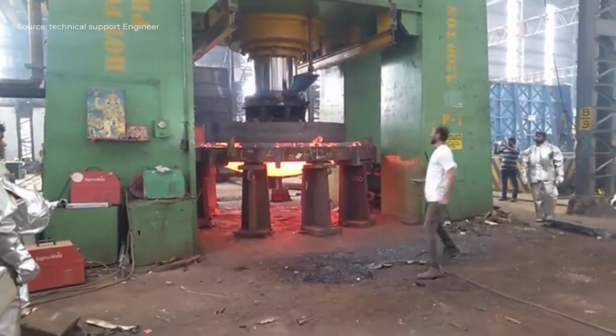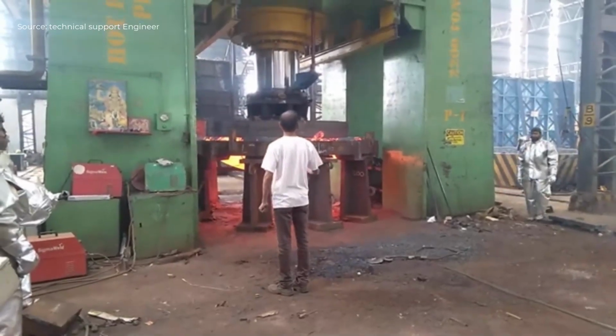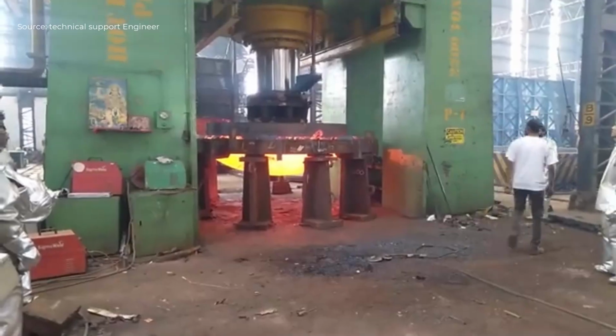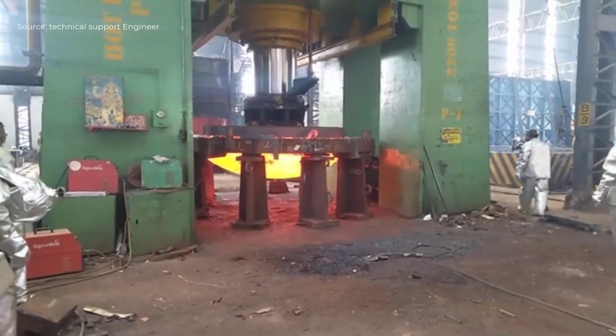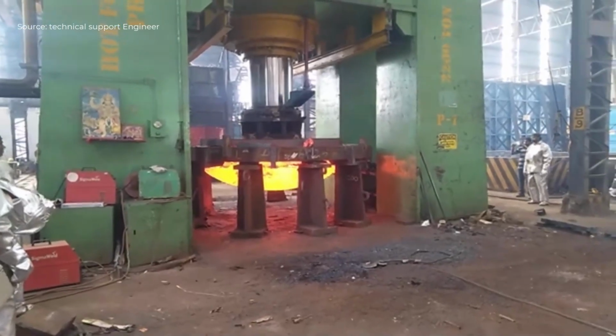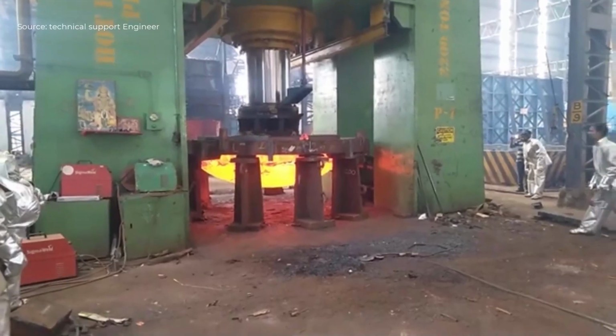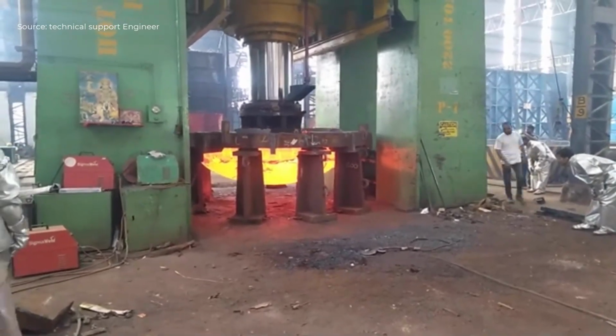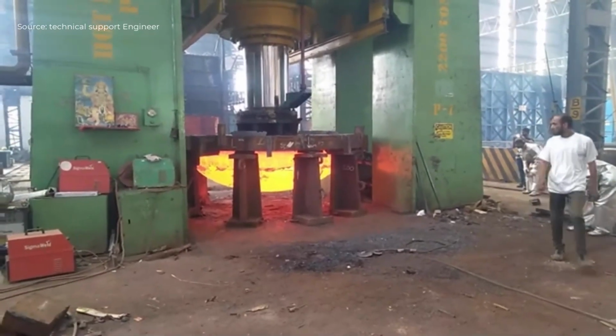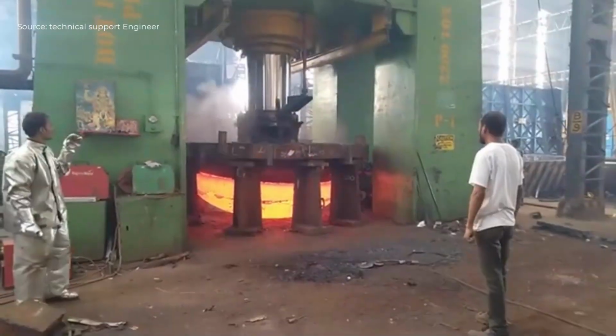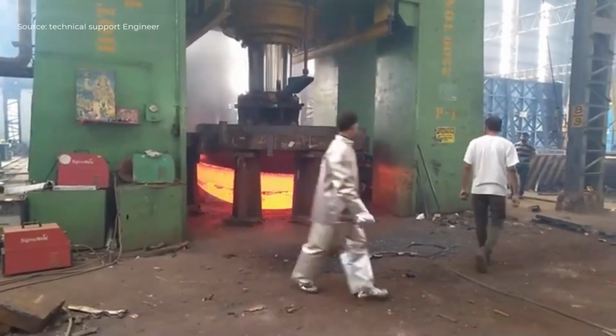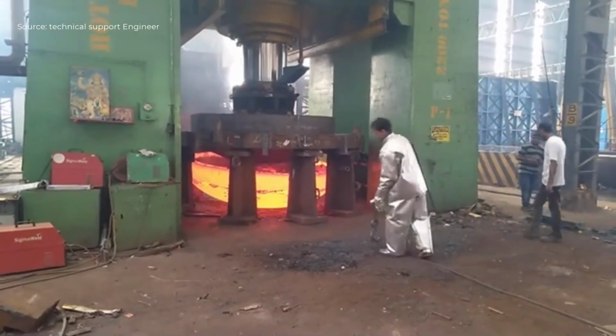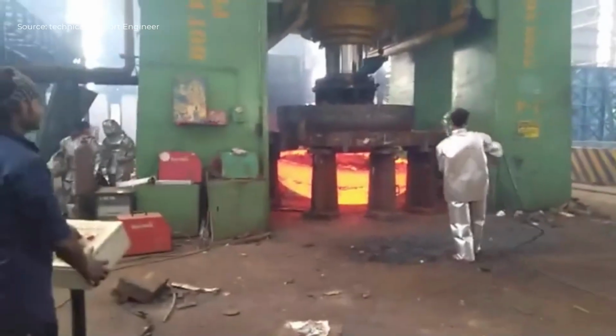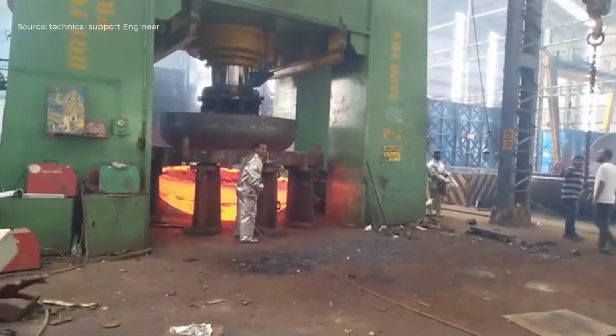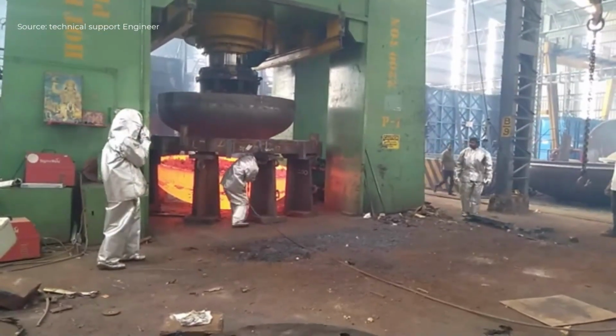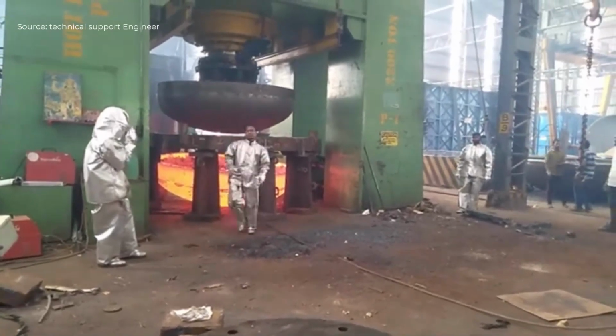To achieve the desired profile, such as ellipsoidal or hemispherical, the plate may go through multiple pressing stages with intermediate reheating if necessary. Throughout the process, operators monitor the alignment and positioning to ensure symmetrical forming. After pressing, the dished end is removed and allowed to cool slowly to relieve internal stresses. In some cases, final shaping or trimming is performed to meet dimensional tolerances. This controlled hot forming process produces strong, precisely shaped dished ends, ideal for pressure vessels and industrial applications requiring high structural integrity.